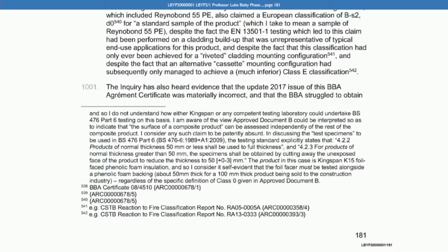In discussing the test specimens to be used in BS 476 Part 6, the testing standard explicitly states that, quote, 4.2.2 products of nominal thickness 50 millimetres or less shall be used to full thickness, and, quote, 4.2.3 for products of nominal thickness greater than 50 millimetres, the specimen should be obtained by cutting away the unexposed face of the product to reduce the thickness to 50 plus or minus 0.3 millimetres. The product, in this case, is Kingspan K15 foil-faced phenolic foam insulation, and so I consider it self-evident that the foil facer must be tested alongside a phenolic foam backing. You go on to say, with measurements, regardless of the specific definition of Class 0 given in Approved Document B.